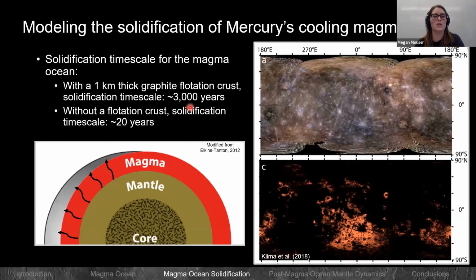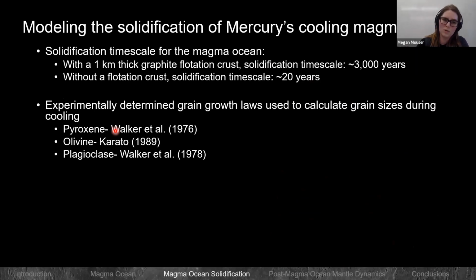But if you don't have a flotation crust, then you don't have this barrier around the surface. So you can just radiate heat out as a black body. So it's going to be a significantly shorter solidification timescale. And so this estimate is a couple of orders of magnitude less, about 20 years. So now we have kind of these end member boundaries in terms of what we could expect for the solidification of Mercury's magma ocean. So armed with this knowledge, the next step is to look at some possible grain sizes that could grow during the magma ocean and during these cooling time periods.